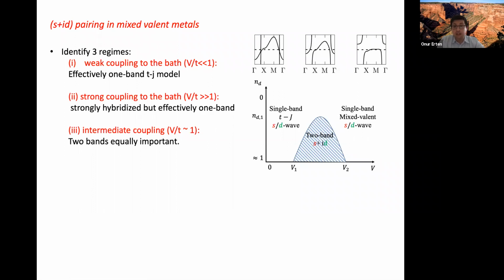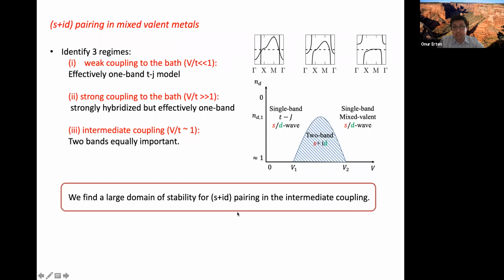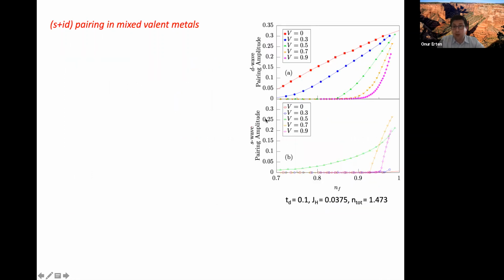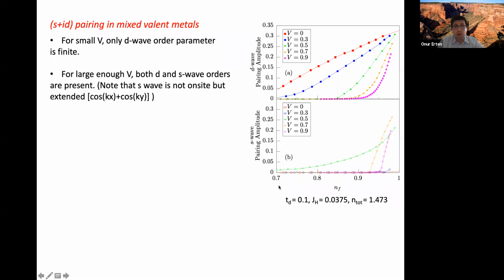And in general, in this region, we find a large domain of stability for s+id pairing. And this is our main result. So how does this come about? These are the real calculations. You can see as a function of the doping, mainly, n_f is the density of the strongly interacting electrons. We find that as we increase the coupling to the bath, so this is the d-wave amplitude, this is the s-wave amplitude. The s-wave amplitude starts to pick up when coupling to the bath becomes order 1. So when the coupling to the bath is small, it's again d-wave as usual, but for large enough coupling to the bath, both s and d-wave orders are present.